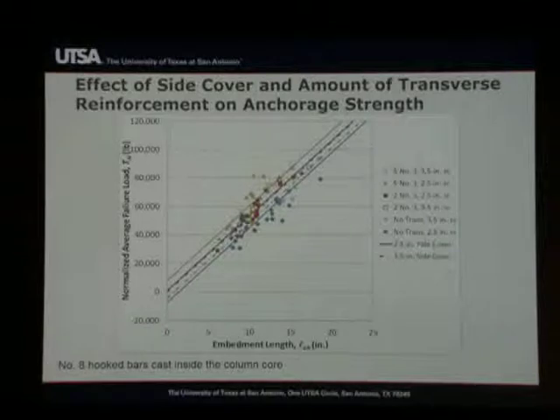Solid lines will tell you what the 2.5-inch side cover does. Broken lines will show what the larger cover does. And so I guess the moral of the story with these is that when we use heavy amounts of transverse reinforcement, the effect of cover is negligible, is not very significant. We do see a little bit of an effect of cover, but it is not overly significant in specimens without transverse reinforcement. So those would be the solid line and the broken line.